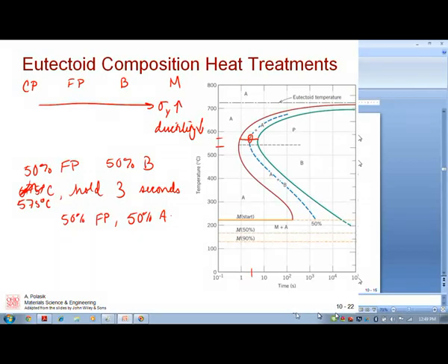The austenite. So it's very analogous to when we started forming, or this step is analogous to, when we would form that blob alpha or primary alpha, and nothing happened to it when we went below the eutectic temperature, right? It stayed. But all of the remaining liquid changed to alpha plus beta, right? So we had liquid plus alpha, but it was the liquid that went to alpha plus beta. So now what's going to happen is the gamma, the austenite, is going to go to bainite. So we're going to cool it down to 400 degrees C.